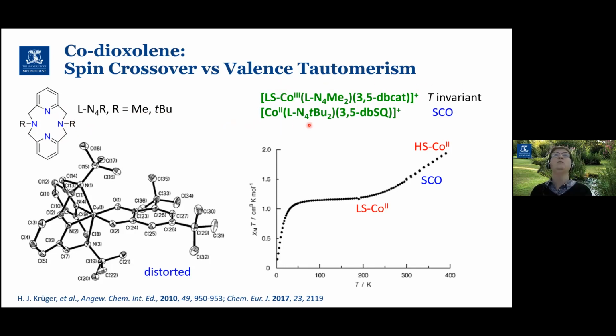On the other hand, when you have tertbutyl groups on that azomacrocycle, now the molecule exists in the cobalt-2 semiquinone charge distribution, but they do see a transition above about 200 Kelvin, and that in fact is a spin crossover transition going from low spin cobalt-2 to high spin cobalt-2. And this is the only complex, the only cobalt-dioxolene complex in the literature that does a spin crossover transition rather than a valence tautomeric or VT transition.